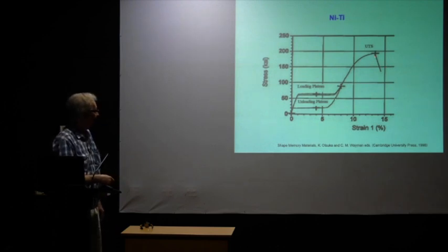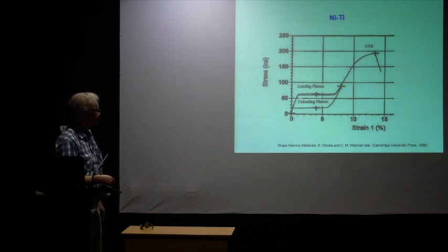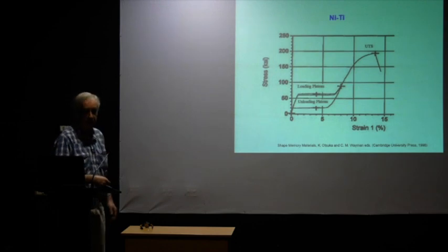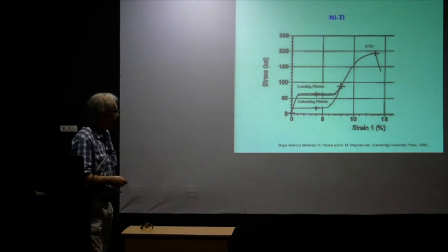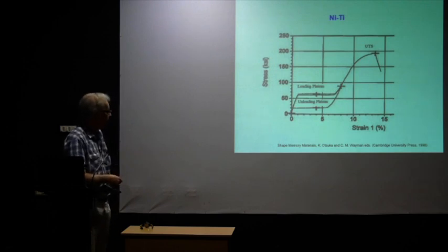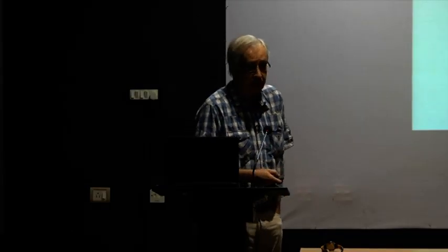If you go back, then you have the loading plateau and the unloading plateau, and there is typically a certain amount of hysteresis involved in that, but this system goes back to its own state. So this whole thing can be viewed as superelasticity.